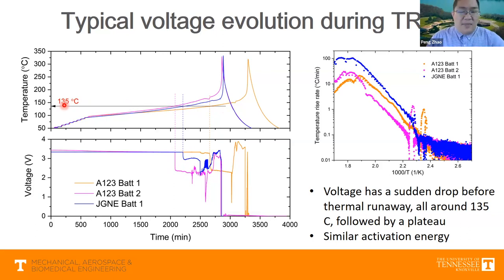And this is not a magic number. This actually corresponds to the melting temperature of the separator, okay? Now based on this temperature and the voltage signal, the question is, can we define some warning signal where we can apply cooling to mitigate thermal runaway and at the same time save the functionality of the cell? And that's what we did.